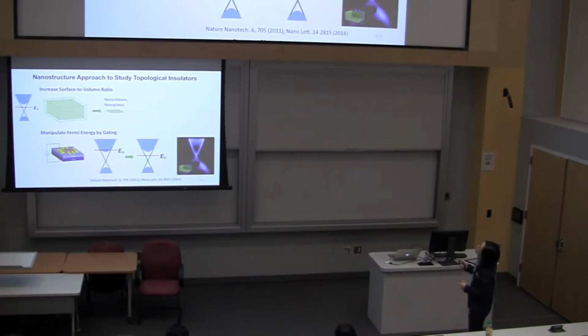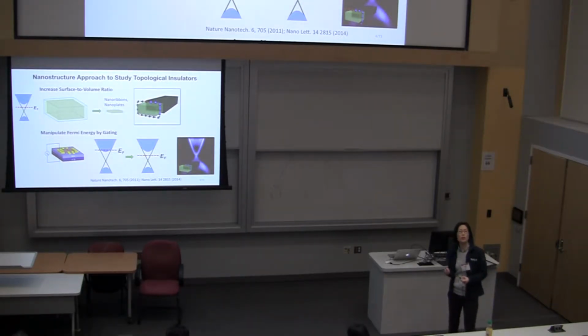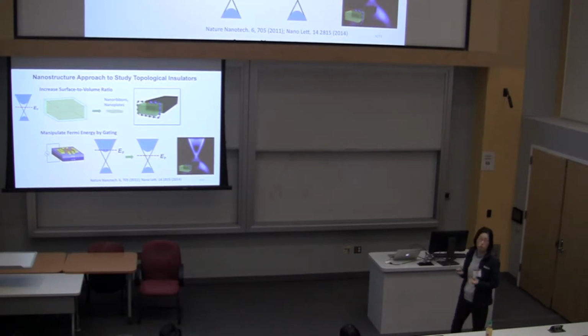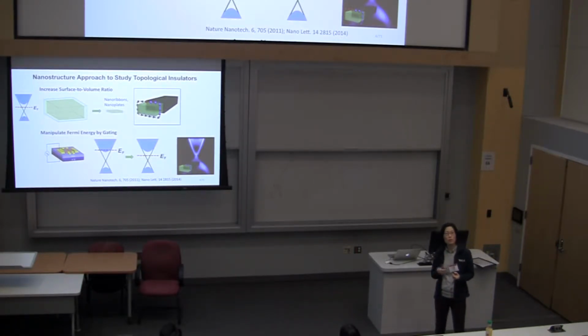Now the distinct advantage of using nanostructures is the fact that you can do interferometry experiments on your surface electrons, right? So the cross-section of the nanowire per se is very well defined by the underlying crystal structure, right? So if it's cubic, you're going to get a rectangular cross-section. And you can then subject your surface electrons to circle around the surface, threaded by a magnetic field, which will then change the phase of the electrons, and now do interferometry experiments, okay?